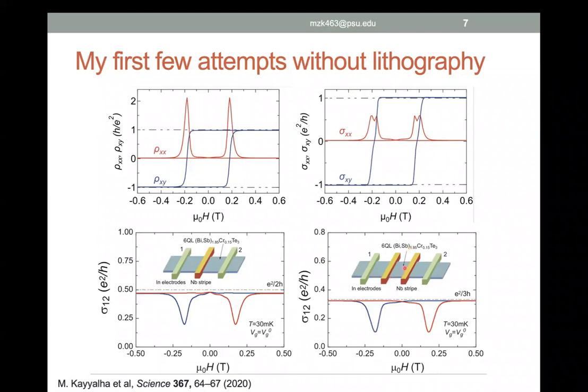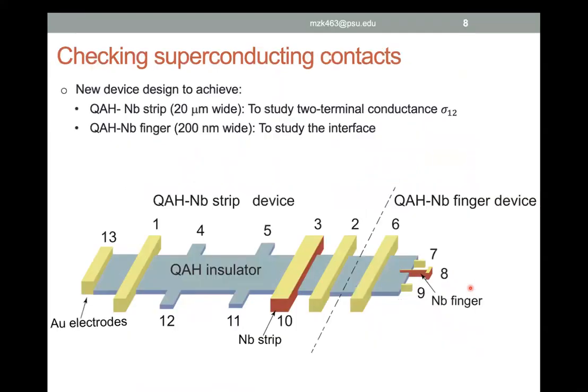But what I saw in the experiment was if I increase the number of superconducting strips from 1 to 2, instead of seeing a half quantized value, I see 1/3. So the sample is now quantized, but at 1/3 of e squared over h. So then I decided to actually design a more systematic sample so I can study everything in one device and actually get a better understanding of what's going on.